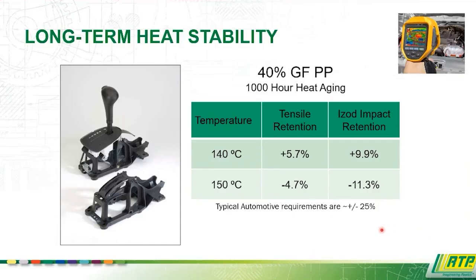Here's a glass fiber polypropylene that's been heat aged at both 140 C and 150 C for 1,000 hours. With the correct heat stabilizers, you can basically maintain those properties for the most part. 150 C, which is really pushing it for polypropylene, can still be maintained to pass what would be considered a typical automotive requirement, or plus or minus 25% retention of those properties.